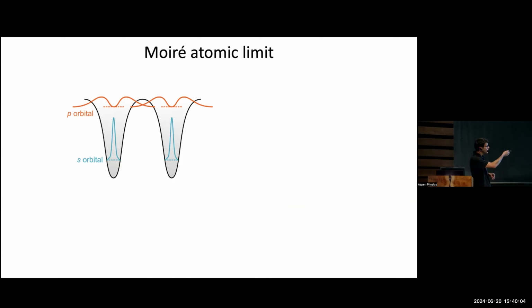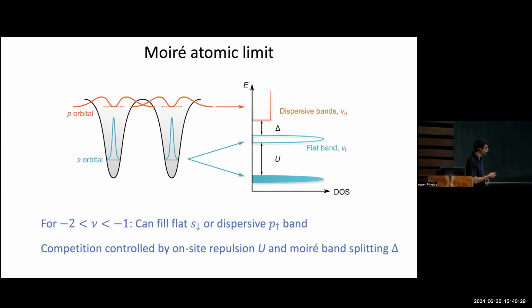And because the wells are so weak, actually, there are additional bound states that behave as though they're p orbitals. These p orbitals are more extended. There's more overlap between them. This corresponds to a higher probability of hopping, that is, a larger bandwidth of the electronic band. So we just ask the question, you start from these eigenstates of quantum well at a time and allow them to hybridize to form a band structure in your Moiré system. What you find is something that looks schematically like this. So there are two s orbitals. One of them is occupied first, and then there's some large energy penalty u corresponding to double occupancy.